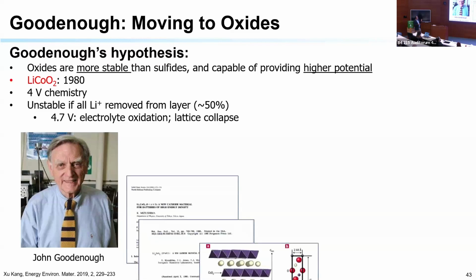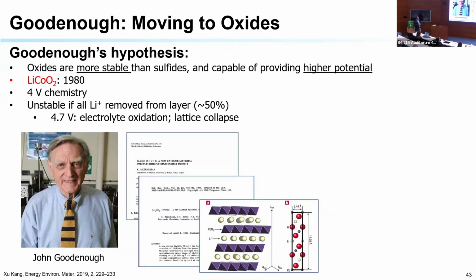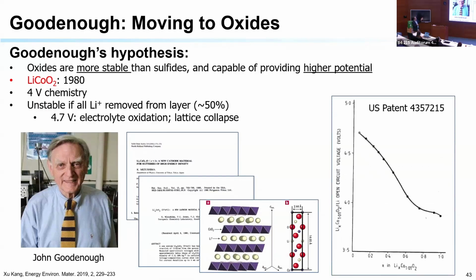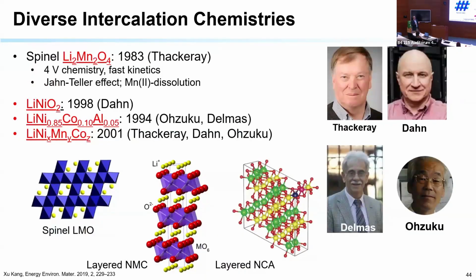He made many new discoveries, actually, and this is his material here, his original paper on the topic. And this is his patent and the characteristics of the battery. Of course, nowadays people dope it and cover it, mix it with things, but this is really the main contribution. Instead of titanium disulfide, you have double the voltage, 2 to 4 volts. That was a huge advancement. After that, a lot of people developed new types of cathodes, layered cathodes, and so forth to try to improve on the voltage or the energy density. And even up to today, this is still an active field. In my group, we work on cathodes with high nickel, and we work on cathodes with different dopants to try to yet improve the energy density. So these are some of the key people who worked in this field.